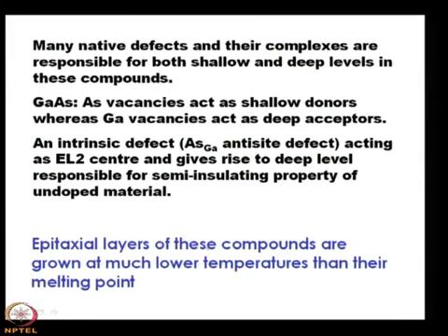And these epitaxial layers of these compounds are grown at much lower temperatures than their melting point. That is also a very important consideration of this 3,5 semiconductor. Say gallium arsenide, the melting point is above 1200 degrees centigrade, but the epitaxial layers are grown at say 600, 650 degrees centigrade.